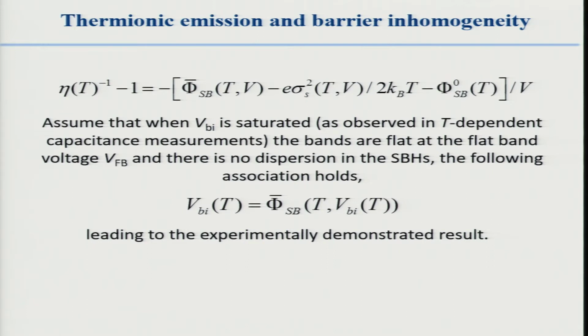You take the inverse, and this is what Werner and Güttler did, and we're just doing it again. And you make this substitution. You assume that the V_BI measurement is saturated. It comes up to a constant value, and especially at low temperature, it slowly increases. You'll see that. And what we do is assume that it's saturated, and where the bands are flat, we're going to call it the flat band voltage. There's no dispersion in the Schottky barrier heights. That distribution has become very narrow. And the following association holds.